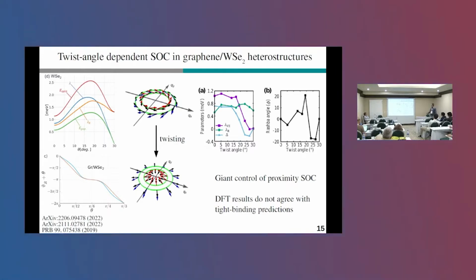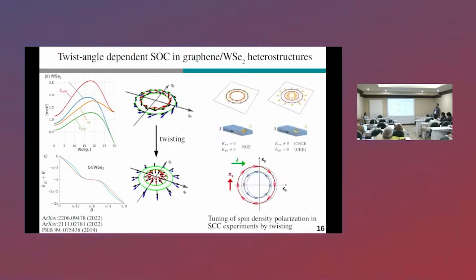So what is the consequence of this radial spin-orbit field? If you do spin-charge conversion experiments, which we have heard of today, and you have the typical tangential Rashba field, then the spin density that you generate will be perpendicularly polarized to the charge current. This is known as the inverse spin galvanic effect or Rashba-Edelstein effect. No matter how you call it, it's the same mechanism. But if you switch into the radial spin-orbit field, you can also tune the polarization of your spin density so that it becomes collinear to the applied current. So with the twist angle, we have actually a knob to tune the polarization of the spin density.